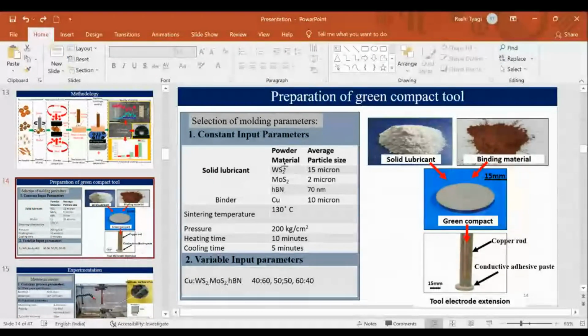So these are some of the parameters that we have used: the powder particle size and average particle size of the solid lubricant WS2, MoS2, hBN powder that we have utilized, the temperature that we have provided, the pressure we have used, and the heating time and cooling time to make the green compact tool.